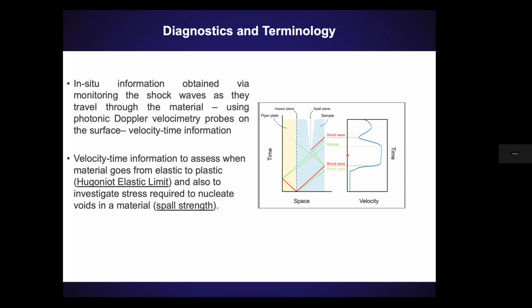So usually this is the primary diagnostic used in shock experiments to understand the dynamic behavior of materials. Like I told you, in our team, we go beyond that and do recovery of samples. The other interesting thing is in a lot of the metals, when you do normal mechanical behavior measurements, there's a yield strength, the elastic to plastic transition stress. Similar to that, there is an elastic to plastic transition under shock. That's called the Hugoniot elastic limit. That can tell you a lot about your material and the deformation mechanisms that are being activated.